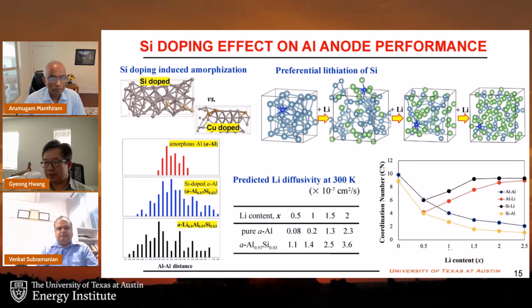In the previous slide, Ram presented that the performance of aluminum foil anode can be improved by adding a small amount of silicon. So we also try to understand how that happens. So when a small amount of silicon is incorporated into this aluminum matrix, we have found that the aluminum structure becomes highly disordered, as shown in the top left figure, but not necessarily all impurities induce the structural disordering. For instance, the copper does not.